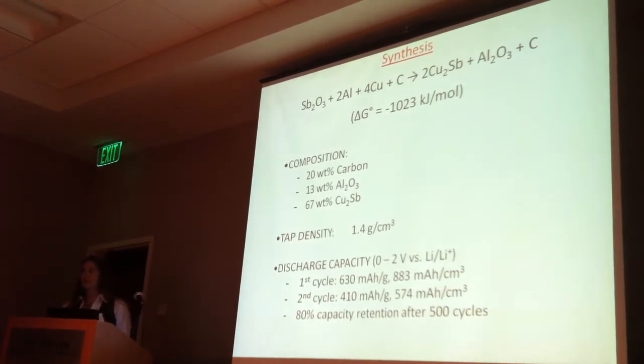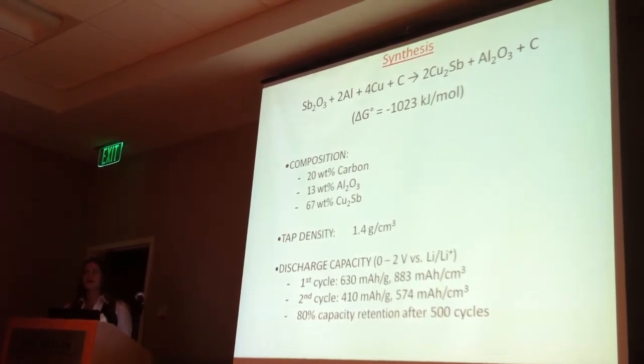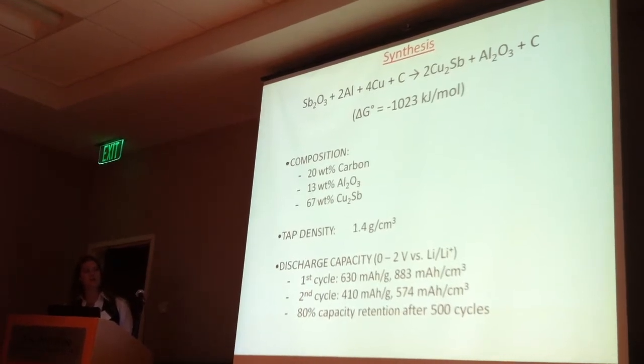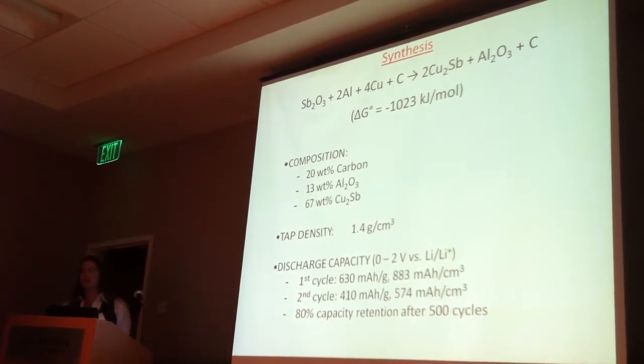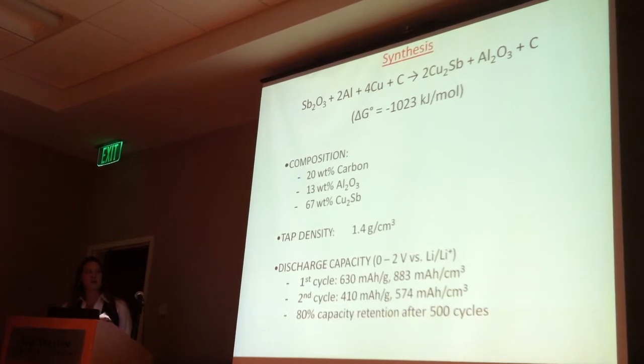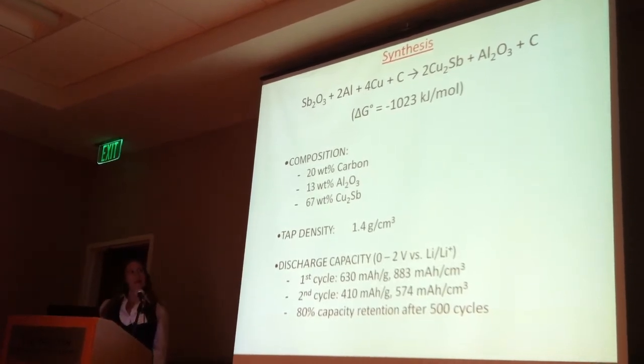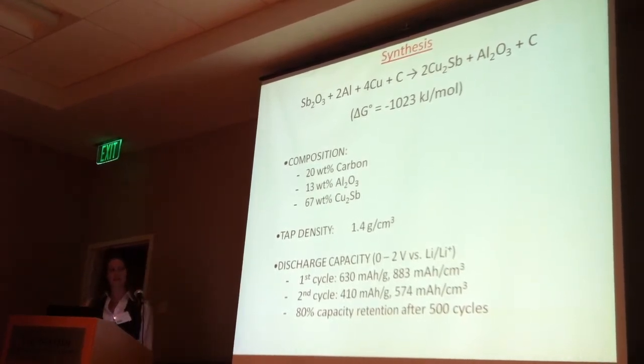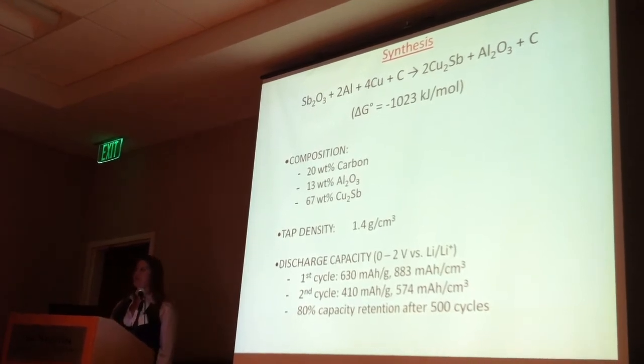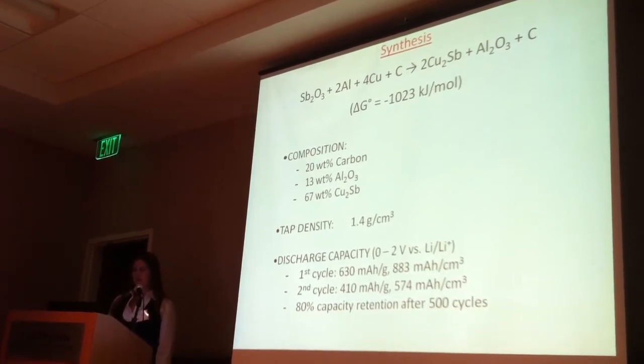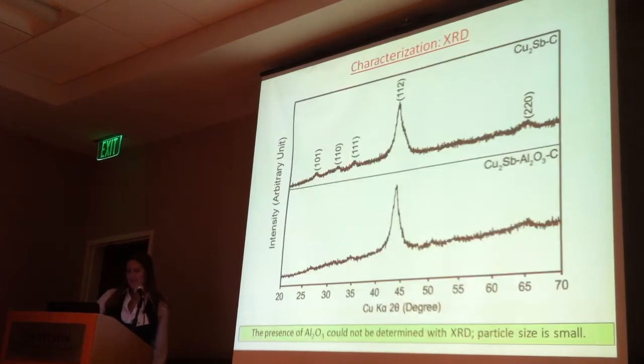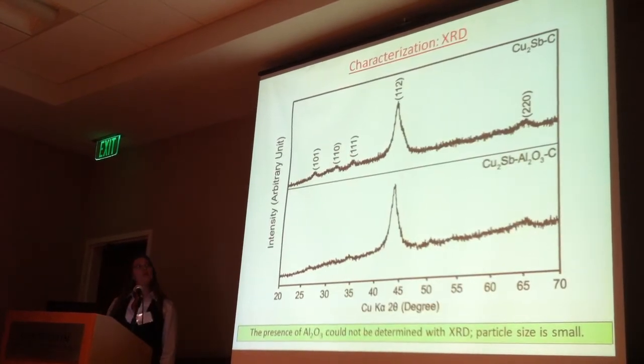Not all of that first cycle capacity loss is irreversible. In this test, we were studying from 0 to 2 volts, whereas the open circuit voltage for this material can be between 2.7 or 3 volts. So not all of that is irreversible. Most notably about this material, and what makes it excellent, is the 80% capacity retention after 500 cycles, which is considered to be stable cycle life.